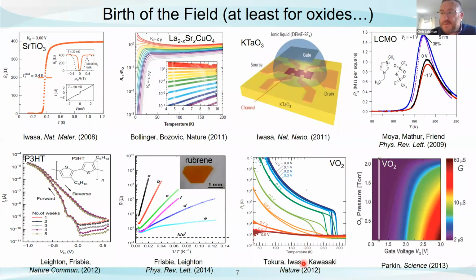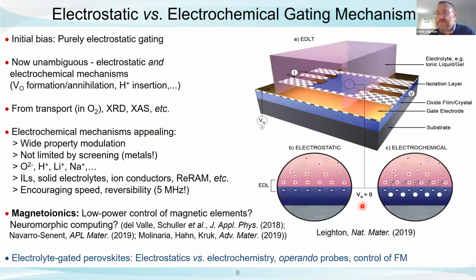So these 3 groups published in 2012 that they had just with a single volt completely controlled the famous temperature-dependent metal insulator transition in vanadium dioxide. This was a very big, important achievement. But just a year later, Stuart Parkin's group showed that those experiments could be reproduced, but that they depend very sensitively on the oxygen pressure during the measurement. And the implication here, very directly, is that the mechanism probably involved oxygen vacancies, not the creation of electrons and holes. So this triggered a controversy which to some extent has never really been fully resolved.